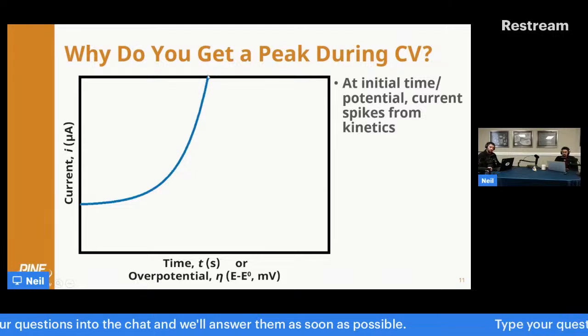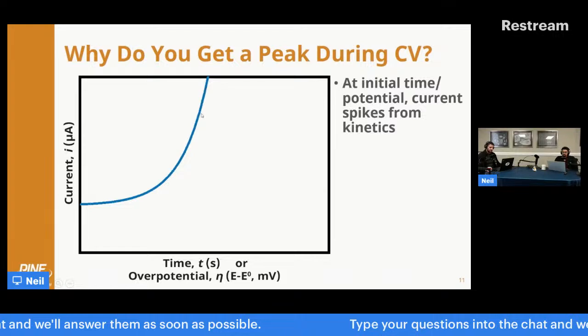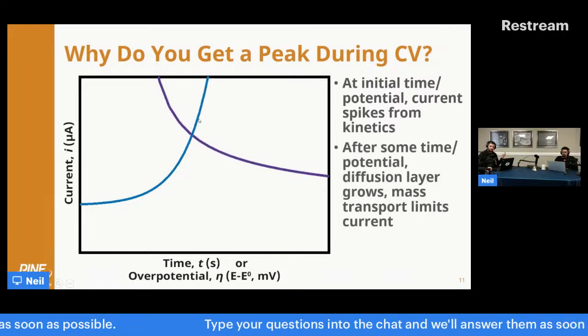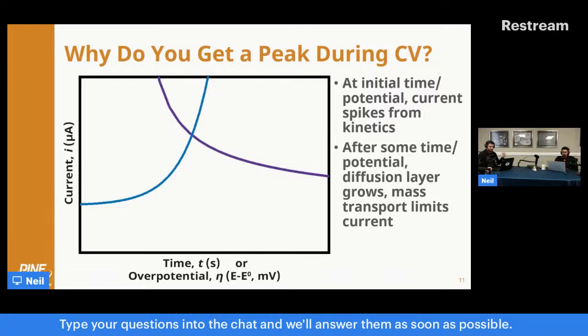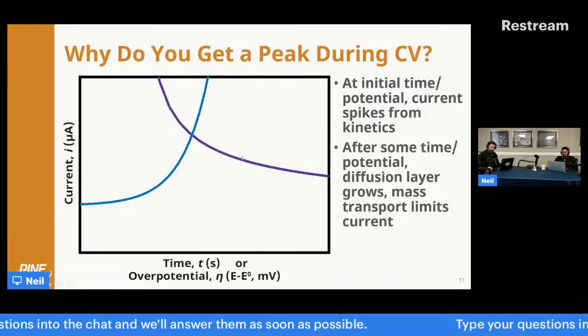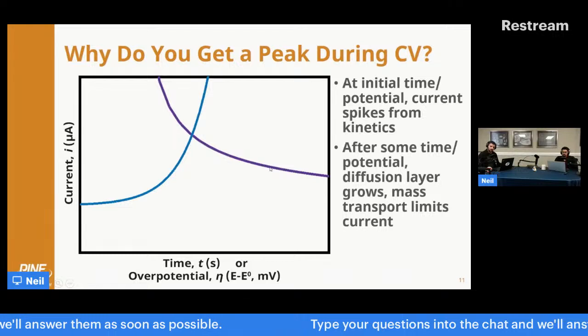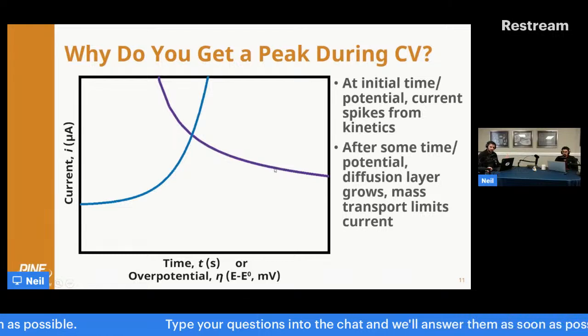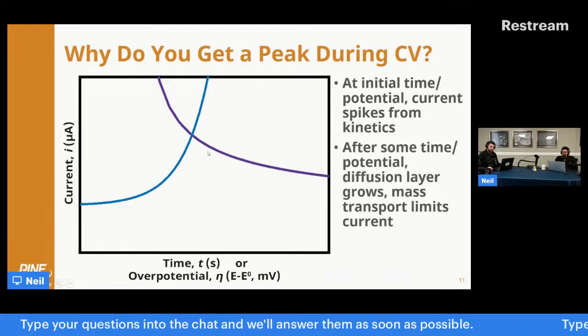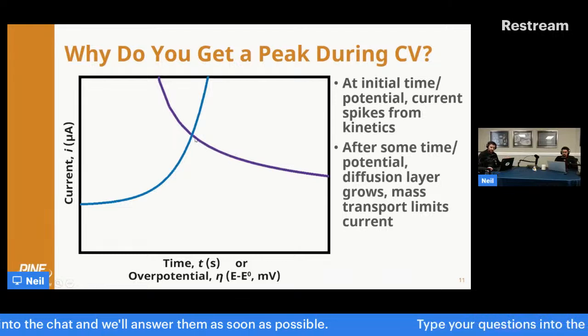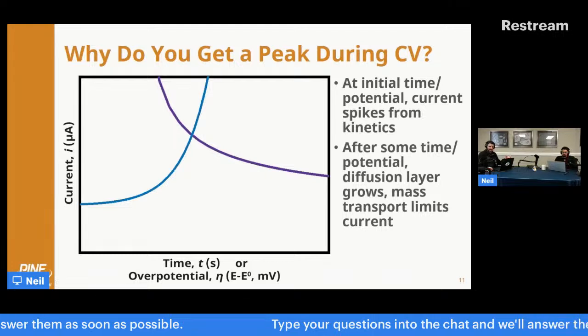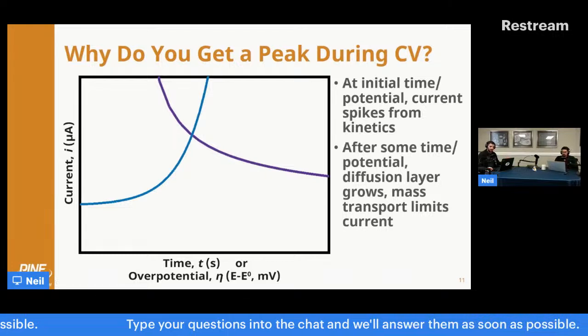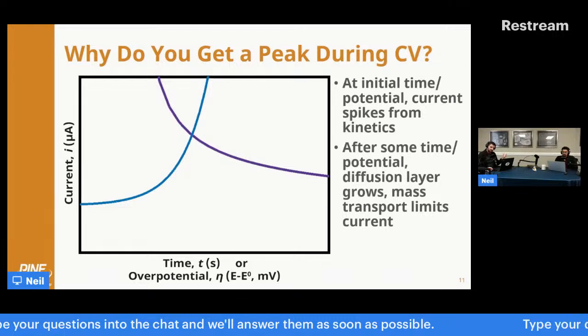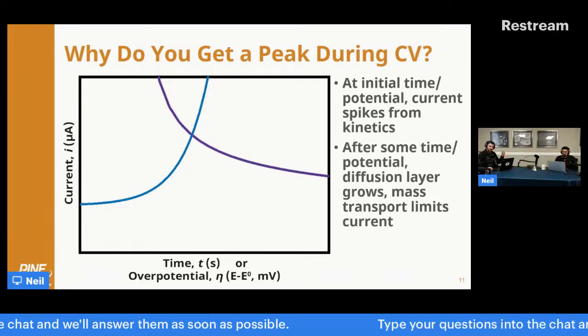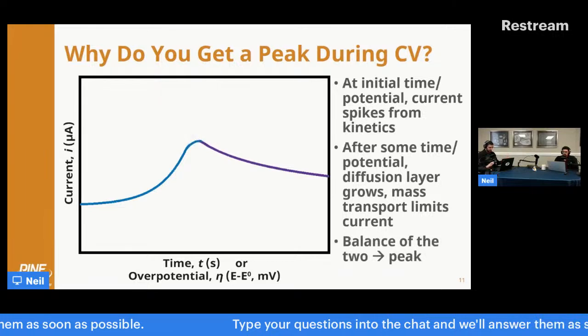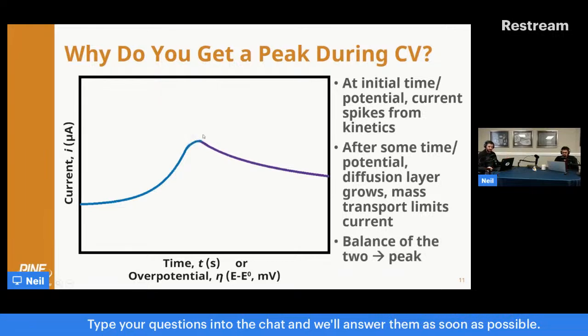However, as I am running this experiment in this reaction, the Cottrell diffusion equation dictates that I should have a decay in my current, because the diffusion layer is growing as I am increasing my potential as well. And so basically, you get a peak simply because at some point in time, something has to give between those two phenomena. Kinetics is causing the current to increase. Diffusion is causing the current to decrease. At some point, there's a balance between the two, and you just physically get a peak.